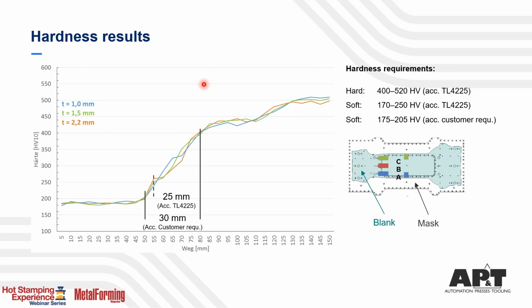What I wanted to show here is a typical technical supplier specification (Technische Lieferantenbedingung) from a German OEM who requires a soft zone, which is defined by limits of 170 to 250 Vickers, and the hard zone, which starts at a lower end of 400 Vickers up to 520 Vickers. We have the graph here. We did hardness measurements over the length in different areas of this B-pillar that you also saw in the video. We tested on the flat surface, on the wall area, and in the flange area